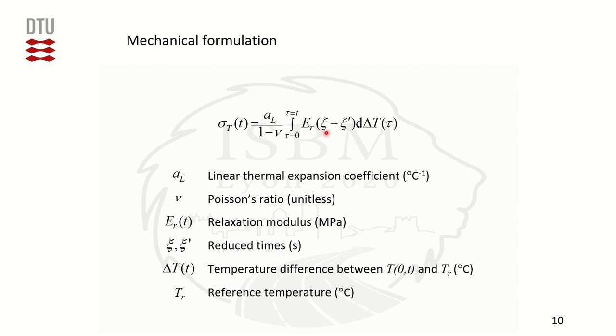This linear viscoelastic formulation utilizes the time-temperature superposition principle, assuming that the half-space material is thermorheologically simple. Additionally, the relaxation modulus function is taken as a 4-parameter sigmoid, and the so-called reduced times are obtained with the time-temperature shift factor, expressed in this work with the Williams-Landel-Ferry WLF equation. The thermoviscoelastic integral equation is solved numerically utilizing the trapezoidal rule with constant time steps of 20 seconds.